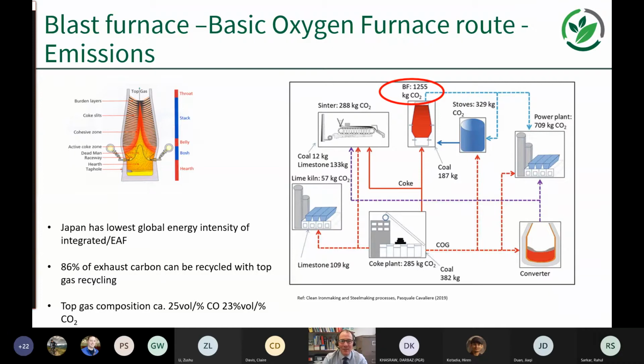So then, looking at producing steel, the iron containing typically about 4% carbon goes into the basic oxygen furnace, where that carbon is combusted off. And overall, in that route for making steel, most of the emissions are associated with iron making in the blast furnace. So I've circled that figure there in the blast furnace of 1,200 kilograms of CO2 per ton of hot metal. Now, Japan has the lowest global energy intensity of this route. But potentially, and this leads on to the evolution of the blast furnace, a lot of this exhaust carbon in the form of carbon monoxide, carbon dioxide, can be recycled through the process to be more completely utilized.